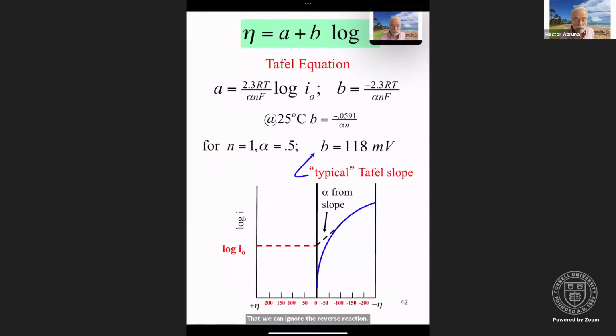And so if we look a little bit further into the Tafel equation, here you have eta equals A plus B log I. A basically has this value, I0, and B has this value. At 25 degrees C, B equals 0.059 over alpha N, which comes as no surprise. And so for N equals 1 and alpha equals 0.5, basically vanilla flavored conditions, the slope will be 118 millivolts, which is considered a quote unquote typical Tafel slope. Basically, it comes from having 59 divided by 0.5 and 1 electron. You divide by 0.5, you essentially multiply by 2. So 59 times 2 is 118 millivolts.